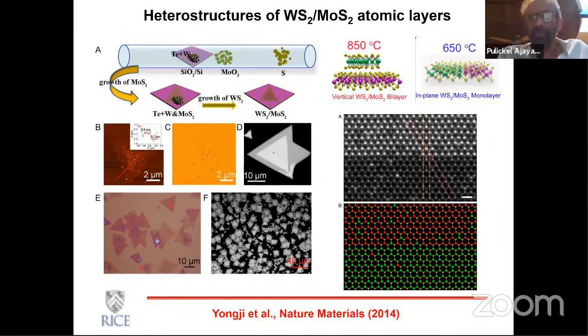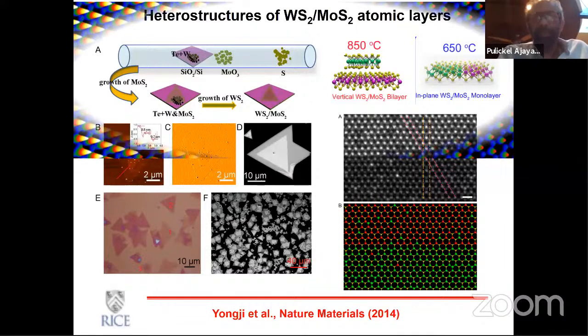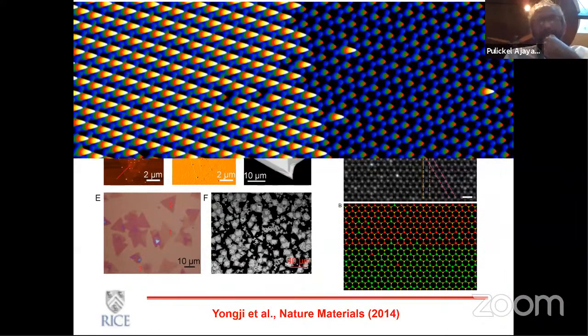You can see these very beautiful, almost atomically sharp junctions that exist between different compositions. This is actually a larger view. And then one wonders, although these are atomically sharp, how stable these interfaces are. We're able to create a very nice junction between, let's say, tungsten sulfide and molybdenum sulfide. How does this junction remain stable? Can you have diffusion across this interface, and under what conditions? So these are some of the questions that we have asked, and obviously you can find some diffusional layer around this interface that changes as you change parameters like temperature.